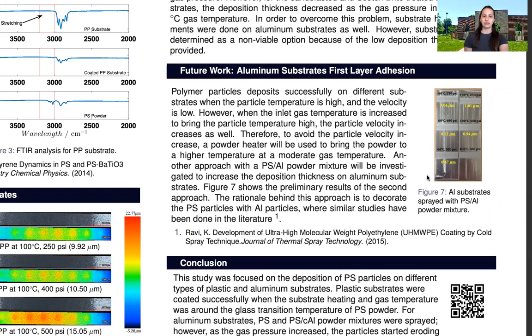This would let the particles heat up, but keep the gas temperature on the low end to keep the velocity low. Another approach we tried, and we will investigate more in depth for the aluminum substrates, is to decorate the polystyrene particles with aluminum particles to help them build a more substantial first layer. Figure 7 shows an image of the aluminum substrate with only 2 passes of coating of decorated polystyrene particles.